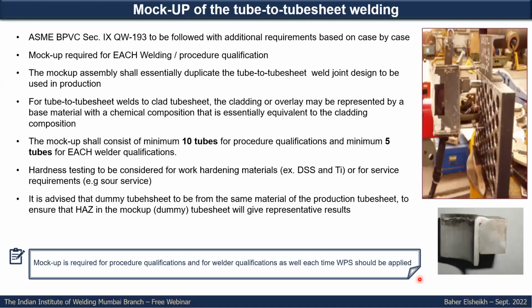And also from the other side, it will mask the results. It will not give you representative results. And we will see one example in the case histories for that. You will apply for some material, the result there will not be highly representative of your actual production, and you might end up with a failure because of that.